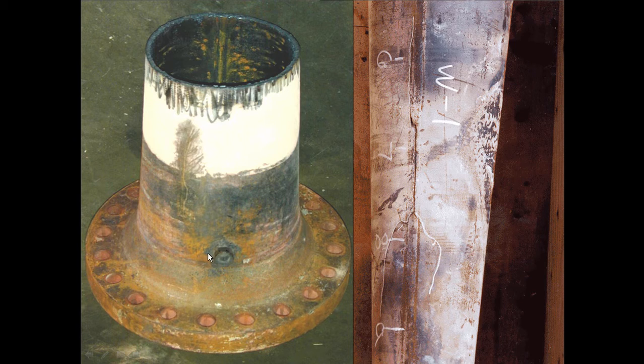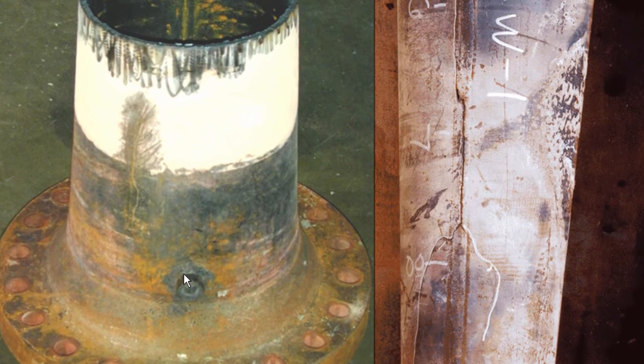Alright, here's the first failure. There's actually a hole here and a crack that goes all the way around, and you can see where the crack propagates into the base material. Over here, here's the second weld. The crack actually starts here. This is the initiation point in the straight area. And it goes in this direction to the toe of the weld and into the base metal, and then right down the center of the weld and makes this big Y pattern.